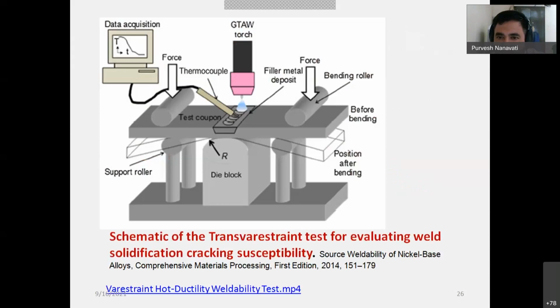So this is a setup for the Transvarestraint test. Now, what do you see? What is your first observation? Your first observation is that the welding direction is changed. Instead of longitudinal, it is transverse. And the die is put well below the weld line. Instead of pressing the plate from the free end, there will be two free ends on either side of this weld line or weld joint, and we apply force from both ends.